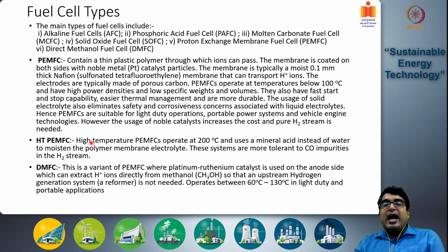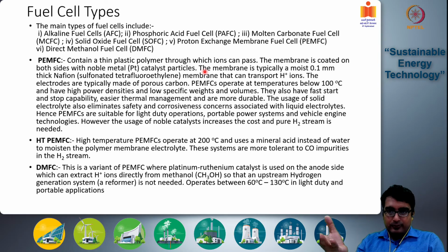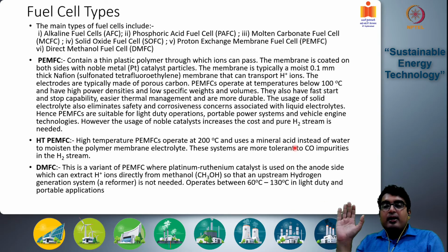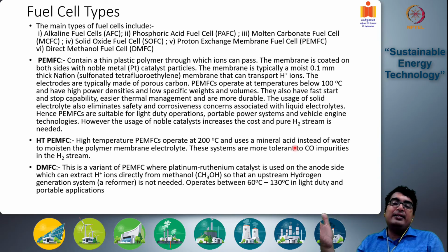Another variant of this is high temperature PEMs. High temperature PEMFCs operate at 200 degrees centigrade and use a mineral acid instead of water to moisten the polymer membrane electrolyte. In the previous case, the polymer membrane electrolyte is moistened by water. In this case, it is moistened by a mineral acid. These systems are more tolerant to carbon monoxide impurities in the hydrogen stream. And operating at 200 degrees centigrade also means that efficiencies are typically higher. So this kind of system can be used for stationary electricity storage systems.